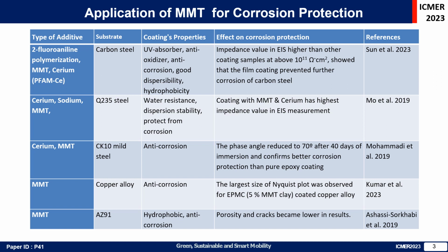This smart coating shows an impedance value in EIS corrosion measurement higher than other coating samples, at above 10 to the power of 11 ohms centimeter squared, which showed that the film coating prevented further corrosion of carbon steel.